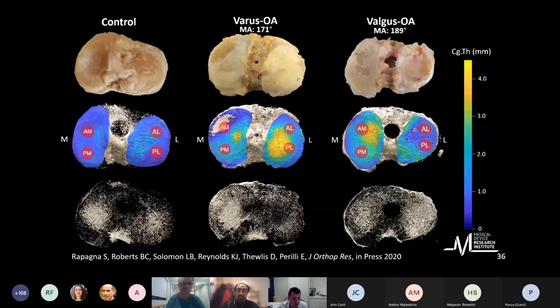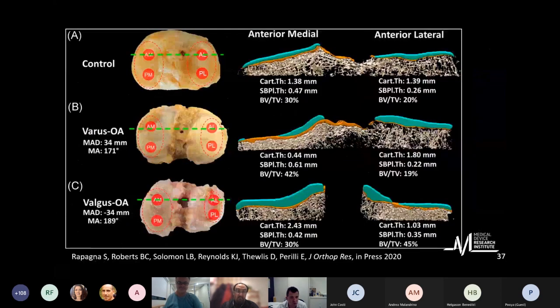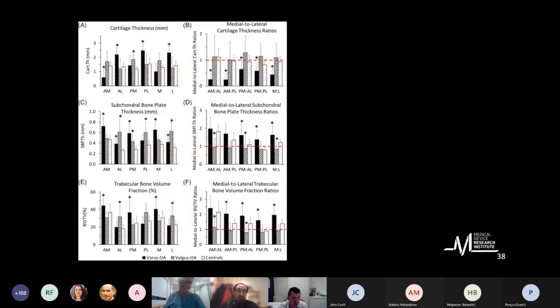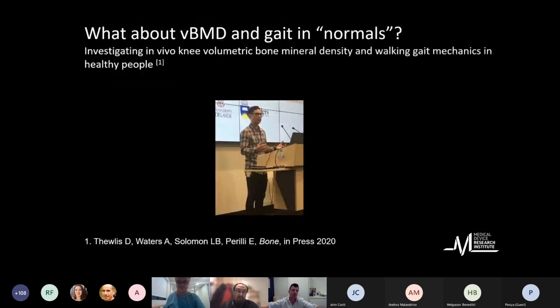And if you look at the bone underneath, we can see that compared to controls, where we have thinner cartilage, we actually have thicker bone, and the opposite in valgus. This is a different view, a coronal view of the same specimens, where you can appreciate, as a cut at the green line, the cartilage is almost gone medially in the first row, the blue part in the second row, and you see very thick cartilage medially in the valgus lines. And these are now the ratios, just showing the statistical significances between the groups that you can actually find in the paper. Now, how do we translate this into clinics?